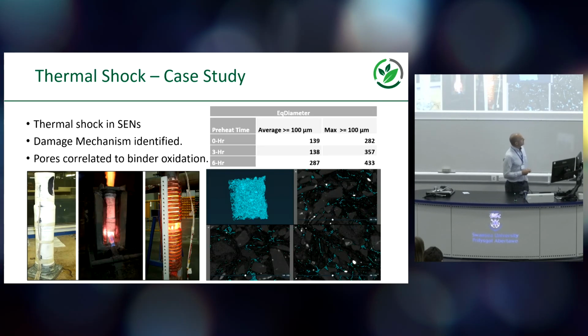Another one is thermal shock, so looking at that other method, so less the effect of carbon and more the effect of thermal shock itself, and actually the interactions between the process of thermal shock and the degradation of the carbon binder. So these are submerged entry nozzles, and this is work we did between Matthew and Ibrahima Salah, who's no longer, when I say no longer with us, he's not dead, but he's no longer part of the group. And we were looking at how we could optimize the preheating of these SENs.